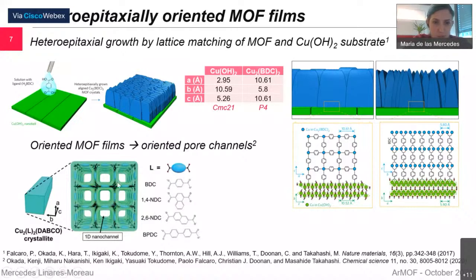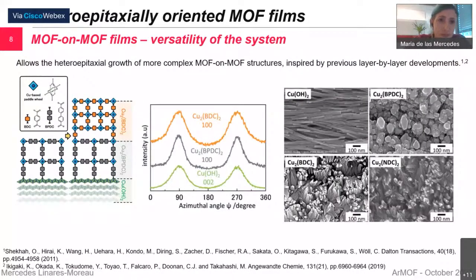applications. So for example, in this work by Okada in Chemical Science in 2020, he studied and showed the growth mechanism for different MOFs with different linkers. This concept was also extended to show that it's possible to have an approach of MOF on MOF, inspired by layer developments like the ones from Professor Wöll. It was also possible to grow heteroepitaxially different MOFs with different ligands, one on top of the other, if the crystal structures were matching.